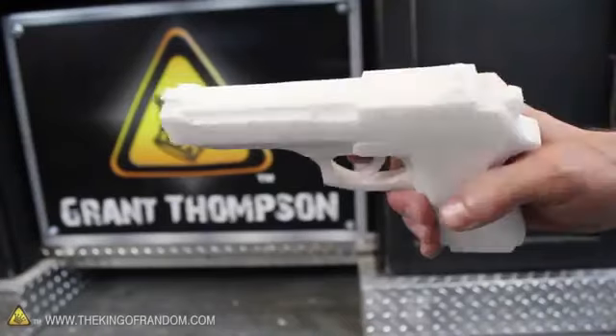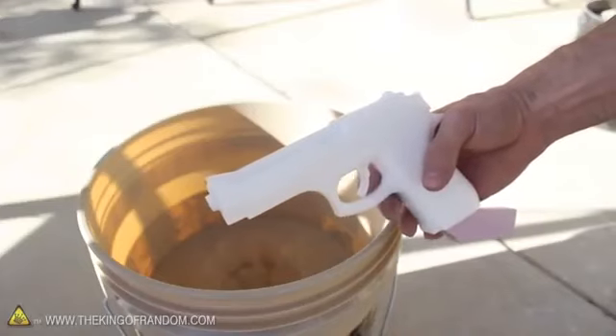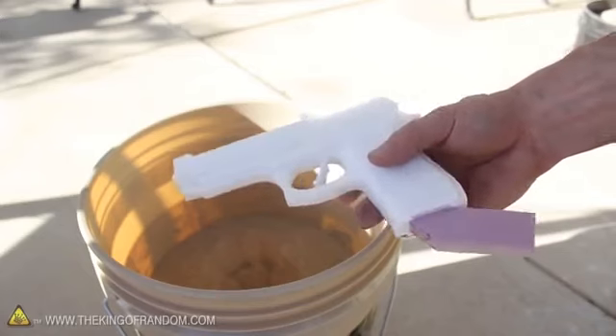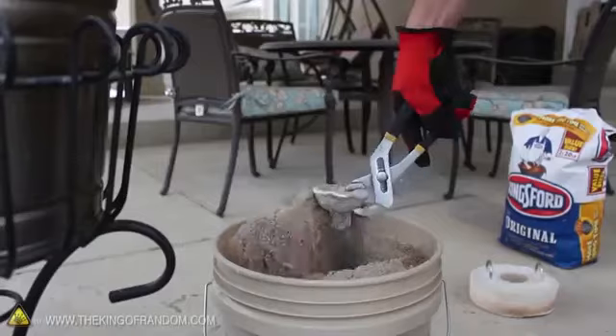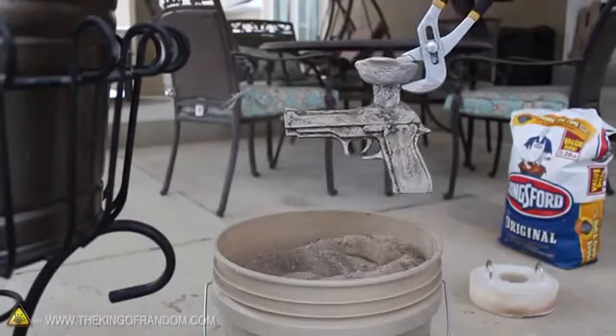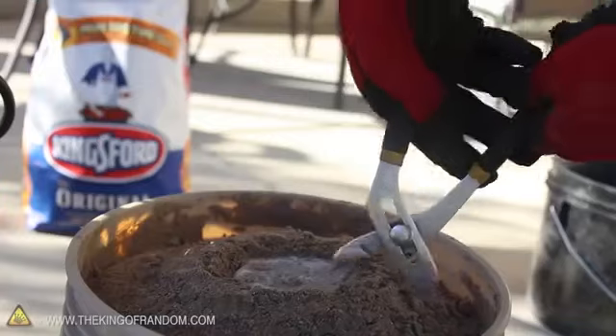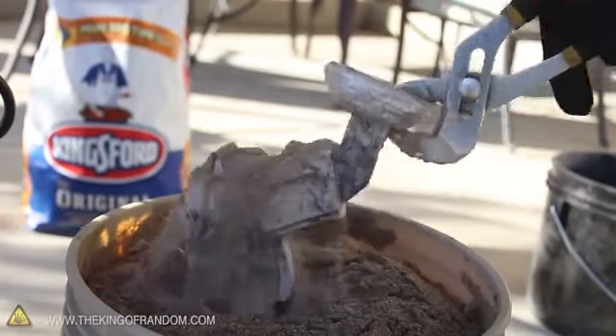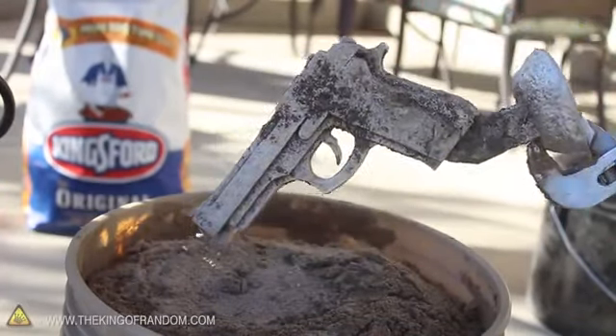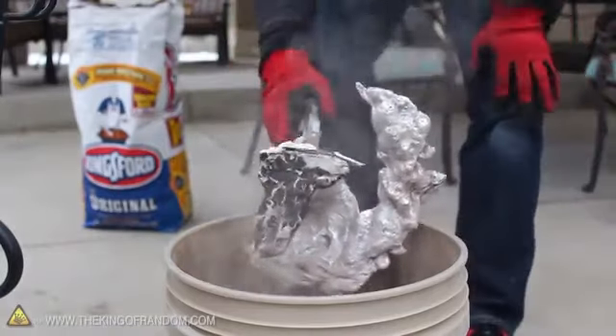Now I want to talk for a second about styrofoam casting. I did styrofoam casting in my previous tutorials because I think that's the simplest method to get started in casting. But it doesn't always yield the cleanest results. It's a trial and error, sometimes it works, sometimes it doesn't. It blows me away that this concept even works at all, that you can just bury styrofoam in sand, pour molten metal and pull out a casting that looks almost identical, but the surface is going to be rough and sometimes the sand collapses and you lose your entire project.